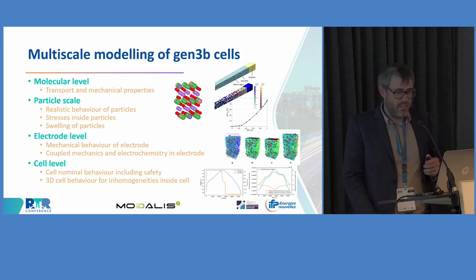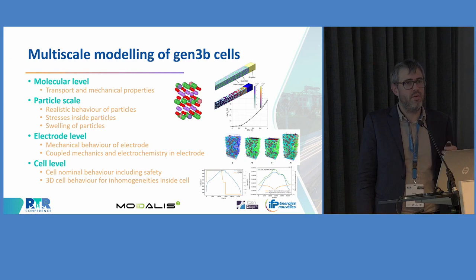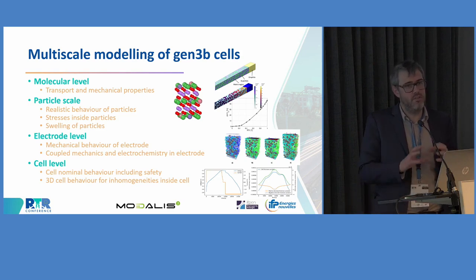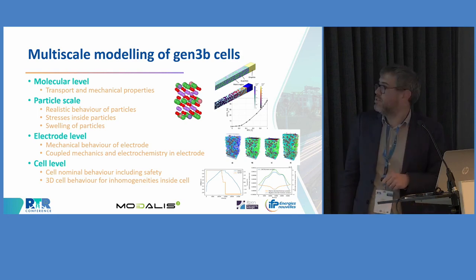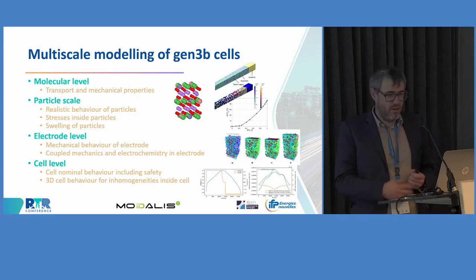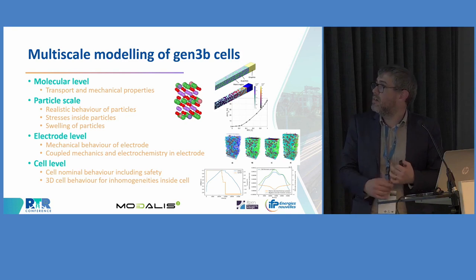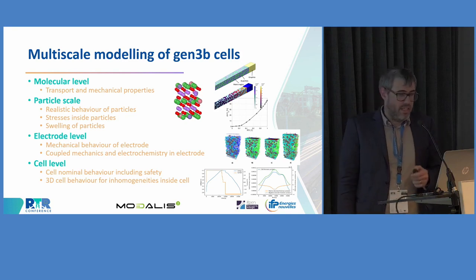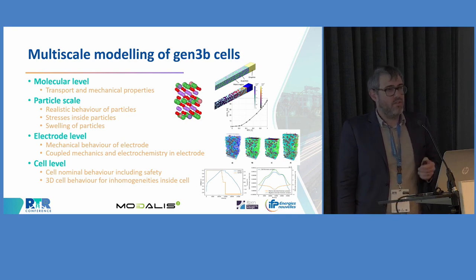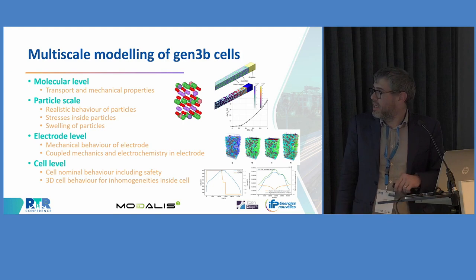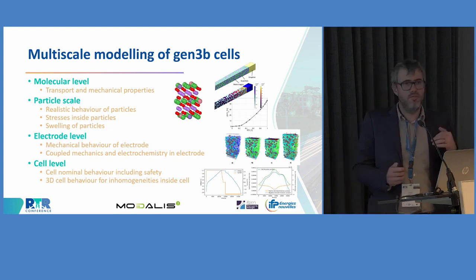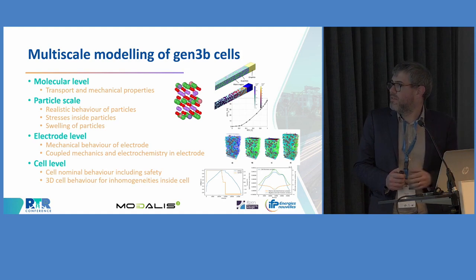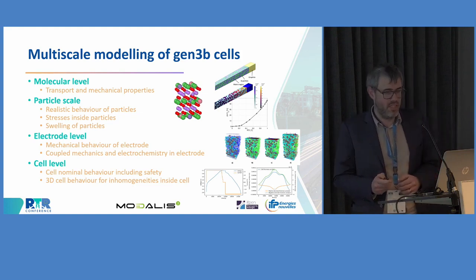Then at the particle scale, as I said, we had realistic behavior of the particles, and we were able to compute the stress generated in the particles due to the swelling of the materials. And of course, the swelling of the particles, as we can see here, was also evaluated thanks to this FEM simulation. At the electrode level, we modeled the mechanical behavior of the electrode thanks to discrete element modeling, as we see here. The aim of this modeling is to see the swelling of the electrode during cycling, and also monitor the bond damages in order to evaluate how much active material was lost during cycling due to mechanical failure.